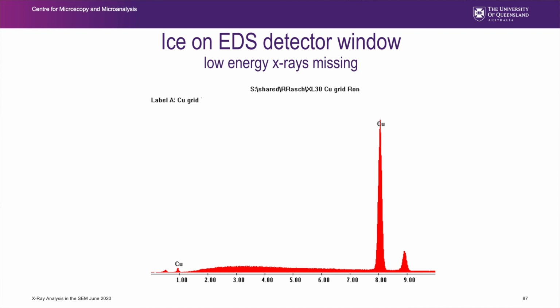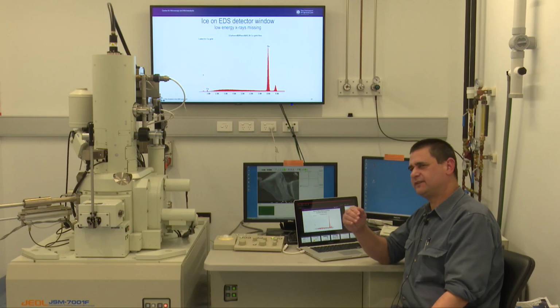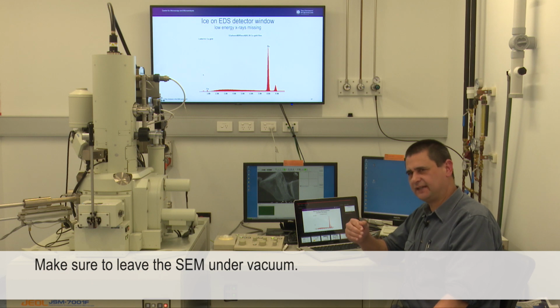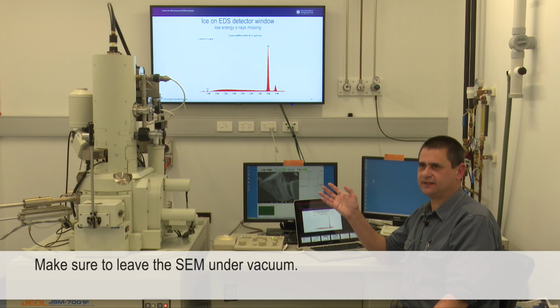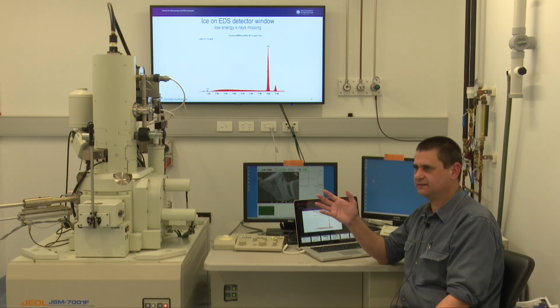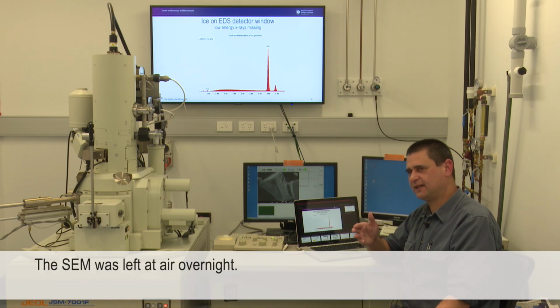What's happened here? I've got my copper K alpha peak, I've got my copper K beta peak. Right here, about 1 keV, which I should be able to see, there should be a very large copper L alpha peak. I don't see it. So what's happened there? We always tell you to leave the SEM under vacuum. And this is a person who finished using the SEM where the whole chamber vented. They were the last person on the machine, and then they went home and they left the SEM at air overnight. That hurts my vacuum system when I'm trying to pump down the next morning.